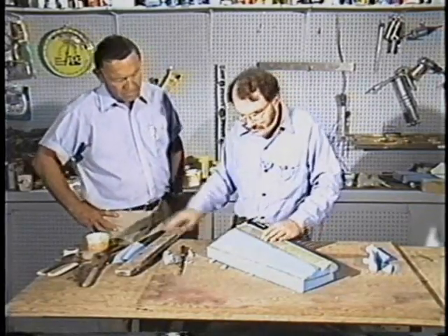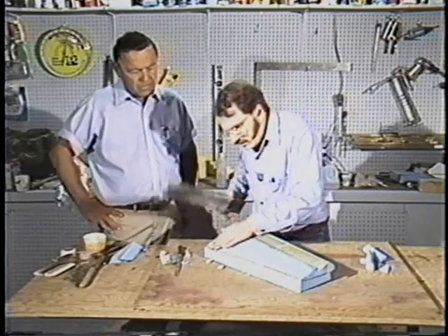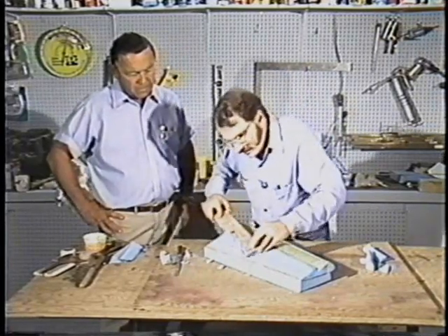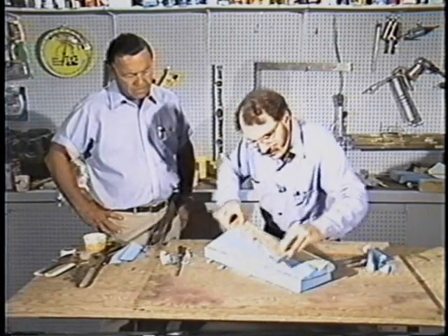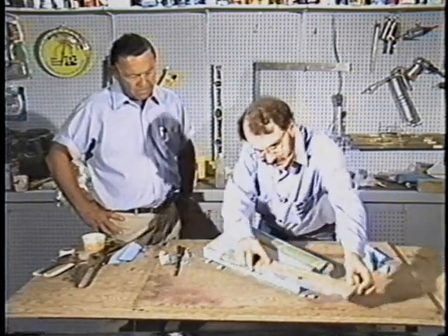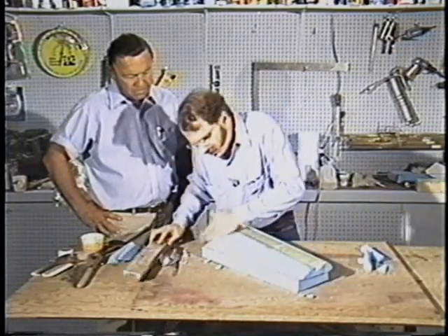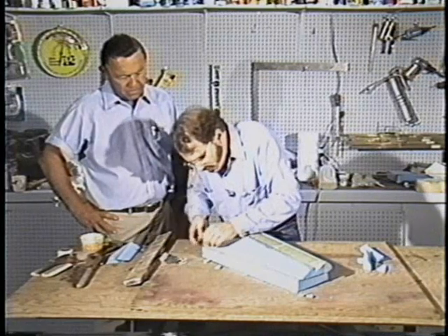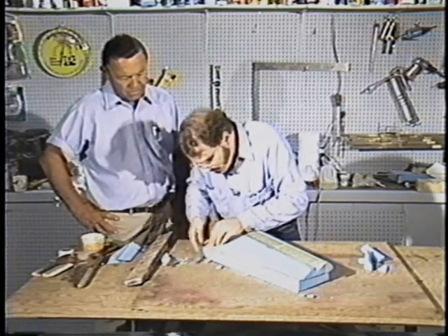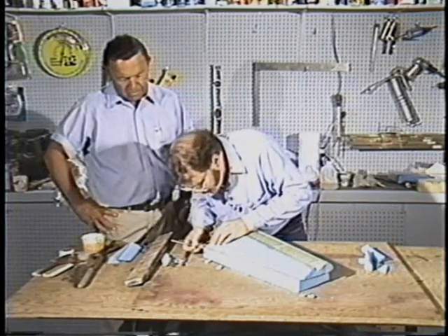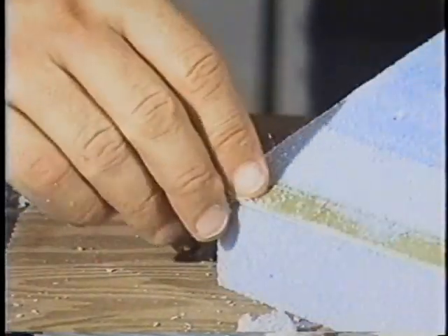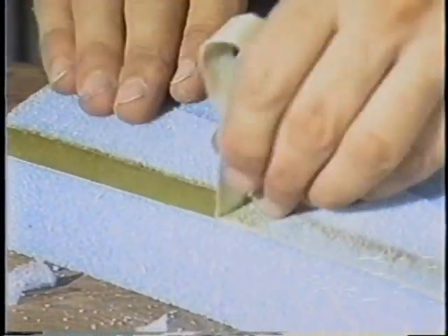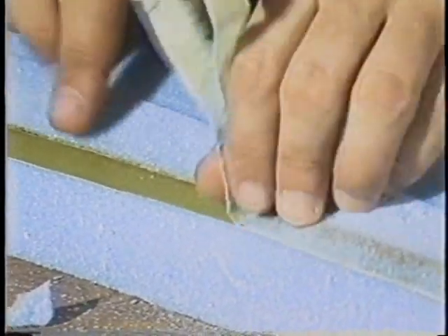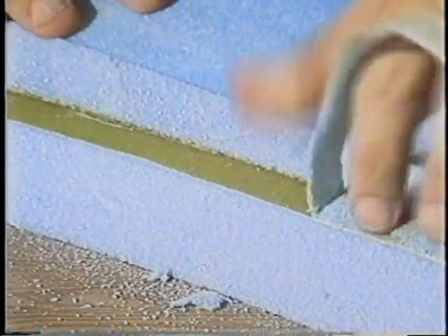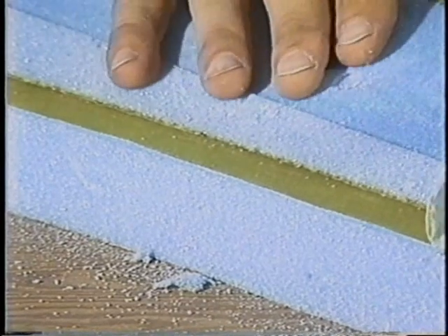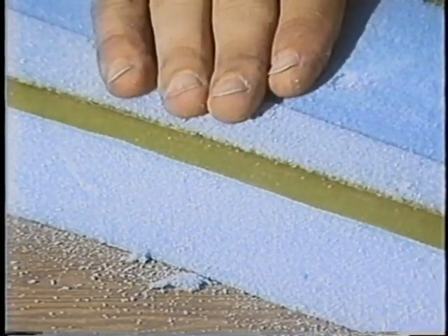Okay, now you've got all that trimmed. Take your long sanding block and you want to carefully smooth this up until it's just about matched in now. Okay, at this point, we're ready to lift the peel ply that we put on with a sticky tape in the previous layup. This will be a little difficult to get started. You may need an X-Acto knife. Once you get it started, you can peel it off, and as you peel, you've got a new fresh surface underneath, which will be perfect for bonding the top skin to. So you get a strong trailing edge closeout. This trailing edge closeout is a critical part of the airfoil.